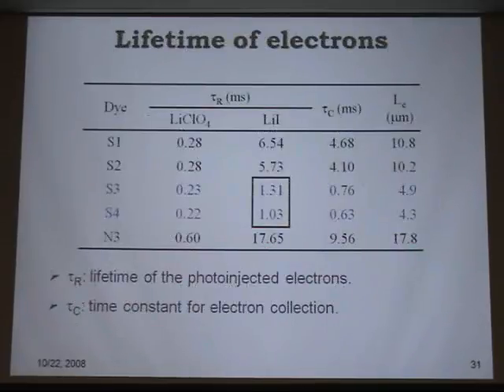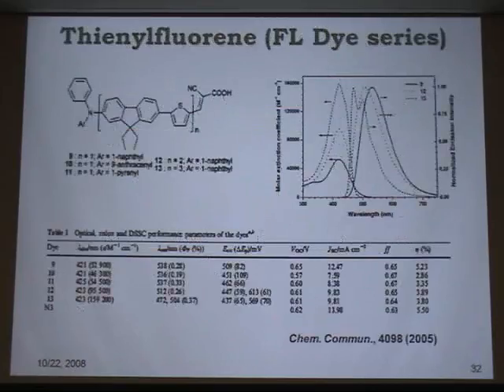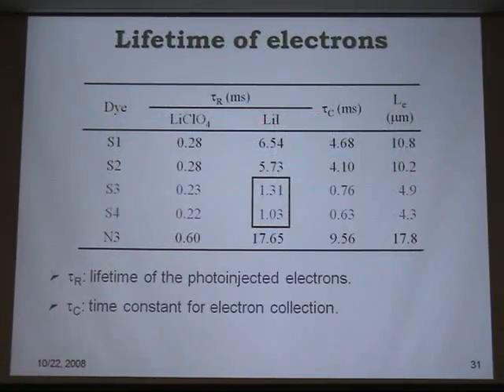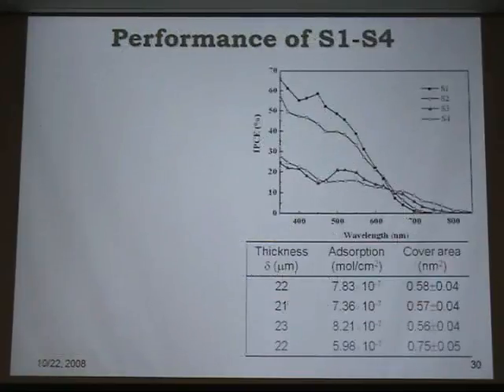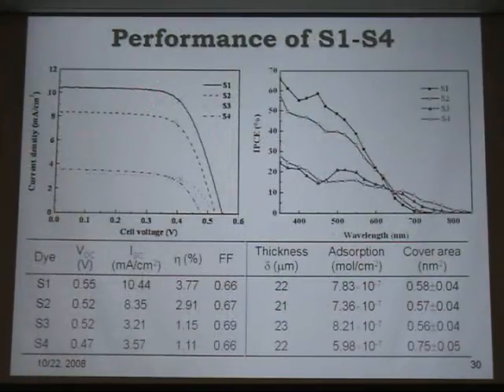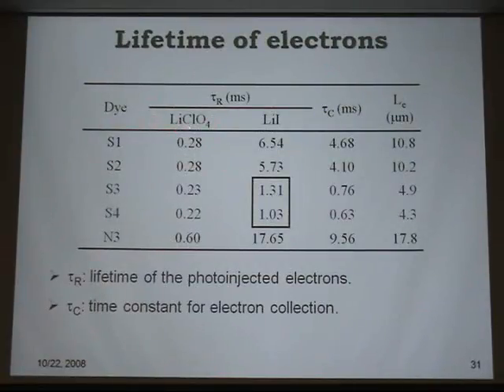So we need to think about the electron lifetime. When you measure the electron lifetime, it tells you that S1 actually gives the highest electron lifetime, 6.5 milliseconds compared to 17 or so for N3. That explains why the efficiency achieved by S1 is still lower compared to the N3 dye. But S3 and S4 are in the same category, and S1 and S2 are in the same category. So that also explains why S1 and S2 are in the same group, and S3 and S4. But if you have this perchlorate electrolyte, now the electron lifetime doesn't tell you the story, but only with lithium iodide.